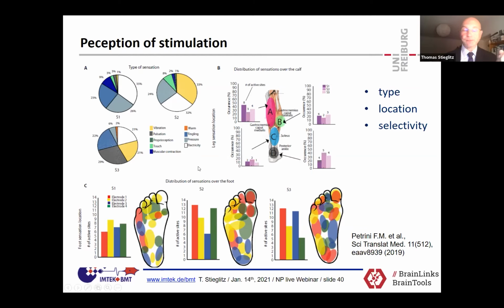As you've seen, we had percutaneous wires. This is still the limiting factor, but when we started that study, we were not sure what the outcome would be. And if you wait for another 5 years to get a fully implantable system, and then you find out that you chose the completely wrong parameters for the electronics inside, that doesn't help at all. And therefore, we thought it's better to investigate that first.